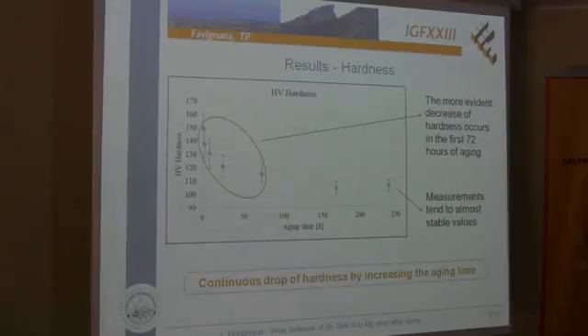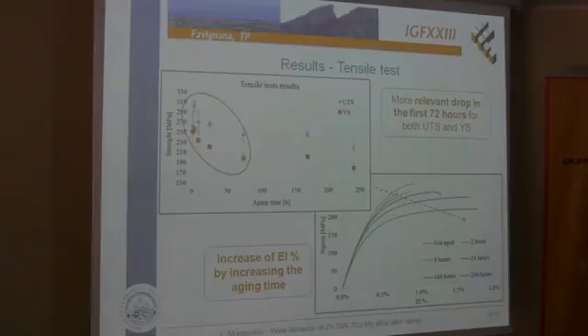Moving on to the results, as you can see in the graphs, the alloy is sensitive to aging, because the hardness decreases substantially during the aging. In particular, in the first 72 hours we have the first and most persistent drop, and then the value seems to reach a stable value. The same behavior was detected after the tensile test.